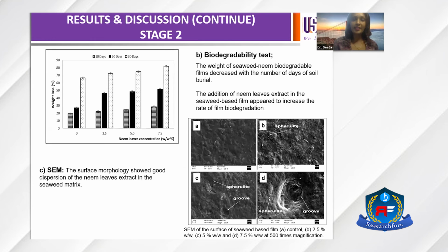Next is the biodegradability test. I used the soil burial test. There is weight loss in the soil burial test, and both the neem leaves and seaweed are hydrophilic, so that can enhance the biodegradability of the film. Lastly, the surface morphology. There is good dispersion up to 5%, but at 7.5%, as I explained for the reduced tensile strength, there are grooves and also holes in the film morphology.